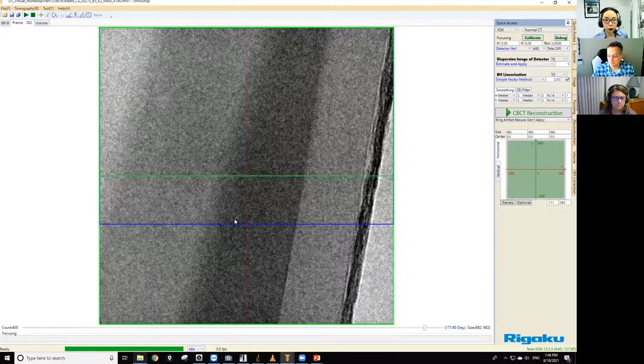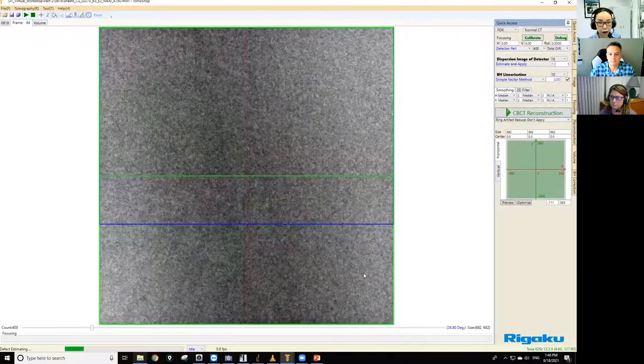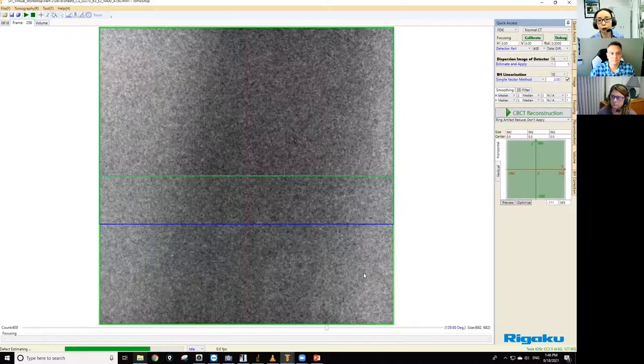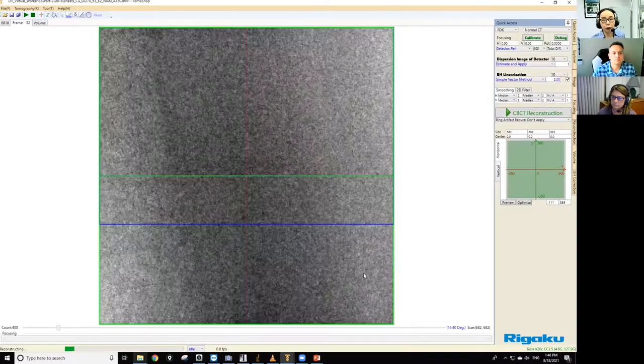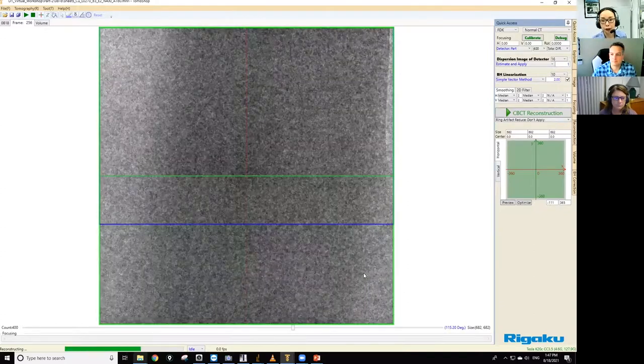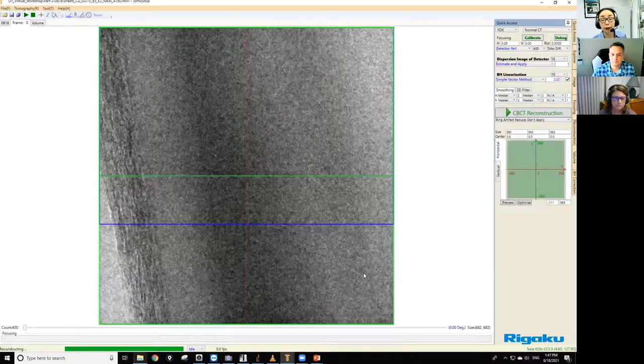But when I say that, we're assuming that the thickness of the sample is the same, because in projections, even if the sample density is the same, if one part is thicker, that part is going to absorb more X-rays. So to really see the density difference, we do have to reconstruct the results. So let me run that. When Angela was doing a similar comparison for glue or sample holding materials, she prepared all materials at the same thickness so that we can do the comparison in 2D. But if the thickness is not uniform, you can't really judge which one has lower or higher density just from 2D projection.